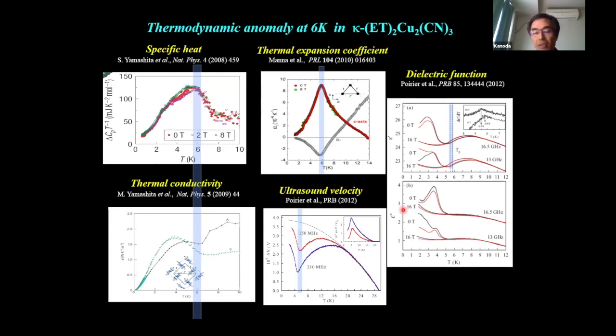Okay, the second issue is the so-called 6 Kelvin anomaly. This spin liquid material shows some anomalies at 6 Kelvin, and that appears in specific heat, thermal conductivity, expansivity, a sharp anomaly in ultrasound velocity, and dielectric functions. So this material shows some thermodynamic anomaly around 6 Kelvin, which is called the 6 Kelvin anomaly.